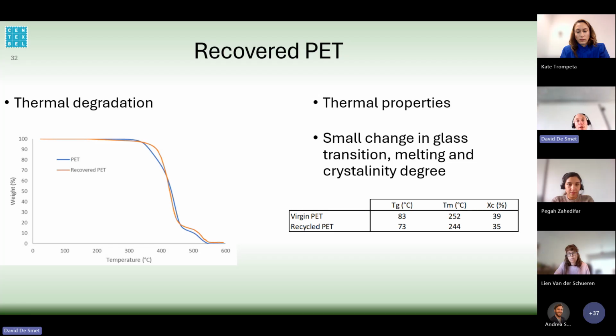If we also look into other properties of the recovered PET, then we see that the thermal degradation of the recovered and the original PET is almost identical. We only saw some small changes in thermal properties like glass transition, melting, and crystallinity degree. We saw that in the case of the recycled PET, there was a slight decrease in the Tg, so the glass transition temperature, the melting point, and crystallinity.